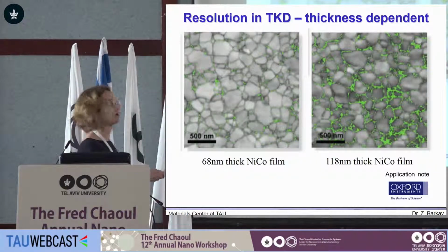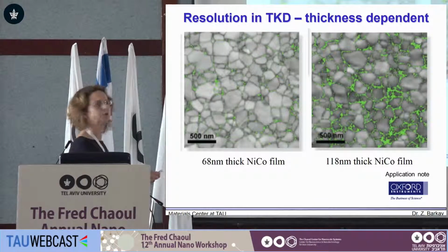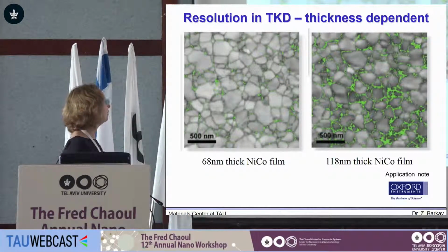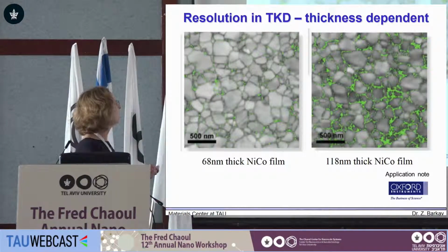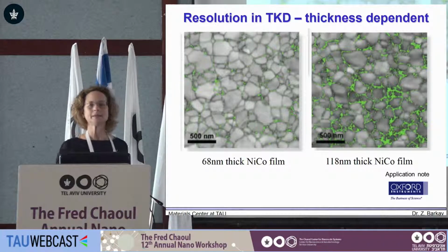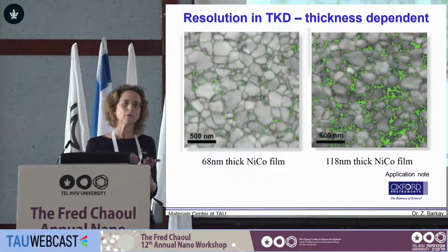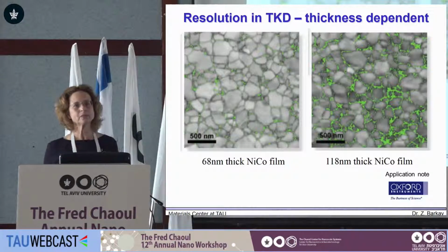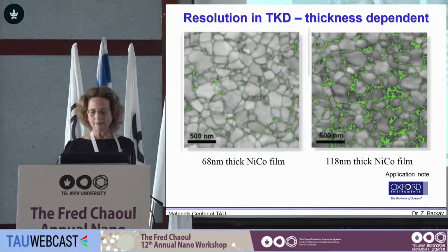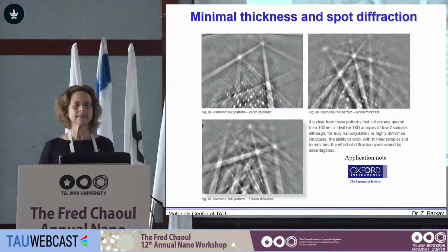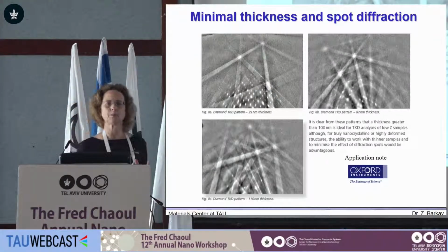But the situation at the moment is the following: if this is around a 100 nanometer thick nickel cobalt film, we have all the unresolved information in green. If we thin it to half, we can have better resolution. So now you may think that we can thin the sample more and more and get better resolution, but it's not that way, because there is a minimum thickness for the whole generation of these Kikuchi patterns.